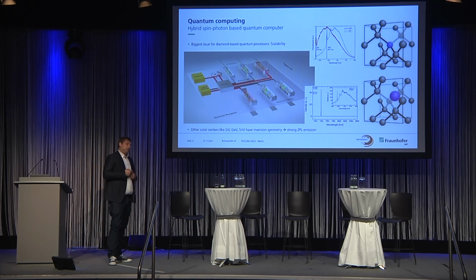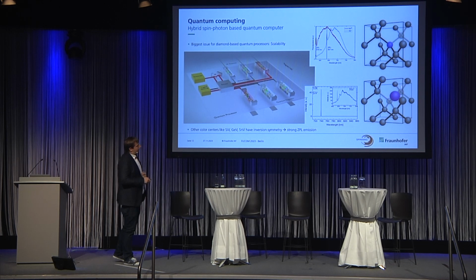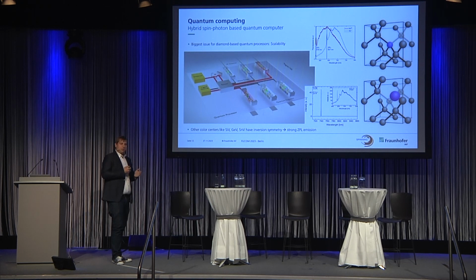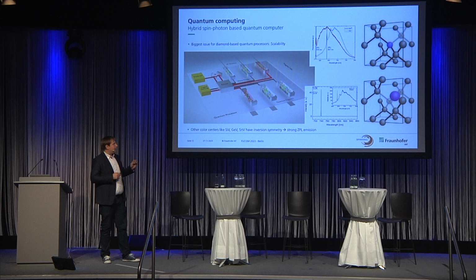Here we are not using NV centers. This is the emission of an NV center. This is the emission of a so-called silicon vacancy center. The difference is the silicon vacancy lies in between two vacant positions and has an inversion symmetry. So the emission is sharp at 738, whereas the NV center has a strong phonon sideband. This is important if you want to couple it to a resonator. You have to make sure that the photons that are emitted from the resonator are indistinguishable. So this is a challenge.